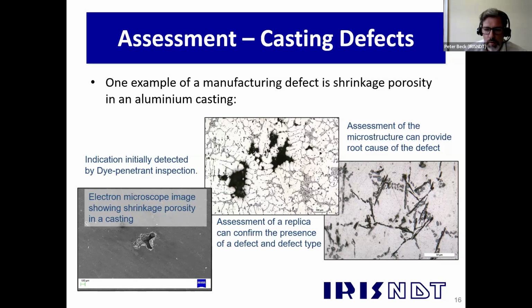So these needle-like phases in the microstructure that you can see, they can tend to slow the metal flow as it solidifies, and that can cause these kind of shrinkage porosities. So all of that is something that we can cover with replication. So we replicate the surface, and we would be able to see these kind of defects and features.